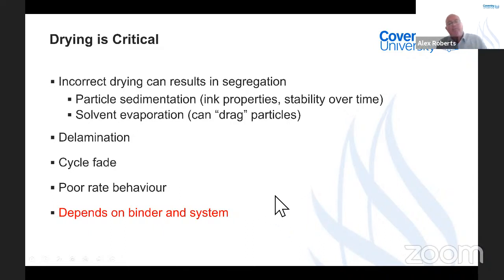And the thing that makes everything more difficult is how hard and how fast you can and must dry will depend on your binder and your system. It's not always the same. So to give you an example from a disaster that I had in some of my work some years ago, working on some supercapacitors that I was scaling up from a commercially bought activated carbon, going for about 900, 1,000 farad cells.